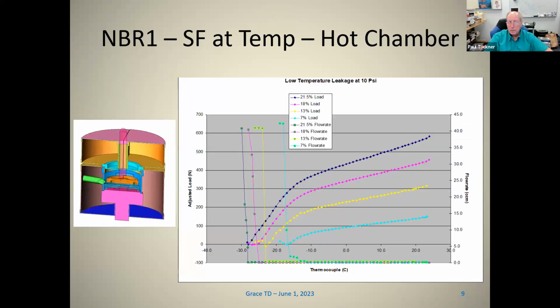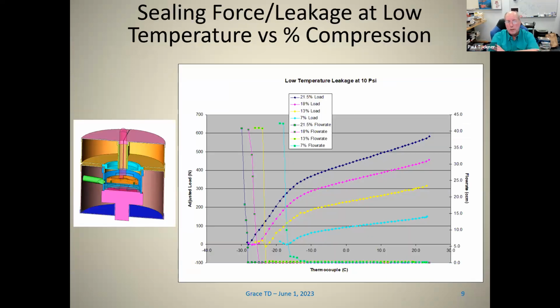This is a picture of the temperature chamber where I did a study evaluating the difference in percent sealing force versus percent compression over a low temperature range. The material was put in there, compressed at room temperature, allowed to sit for 30 minutes, and then cooled down at a given rate to low temperature to note the sealing force.